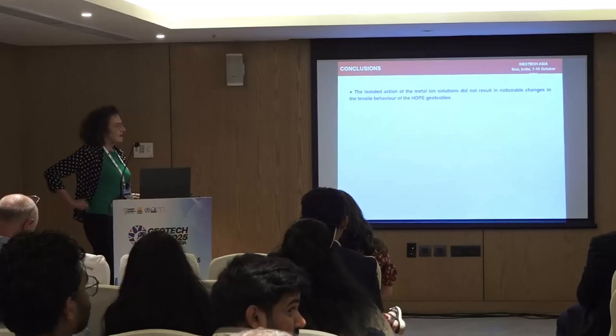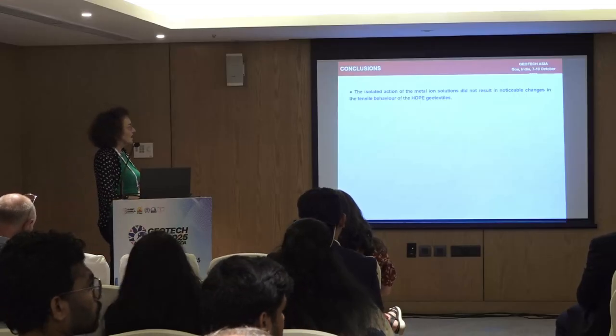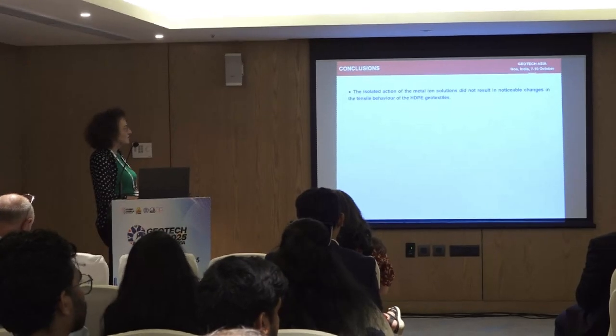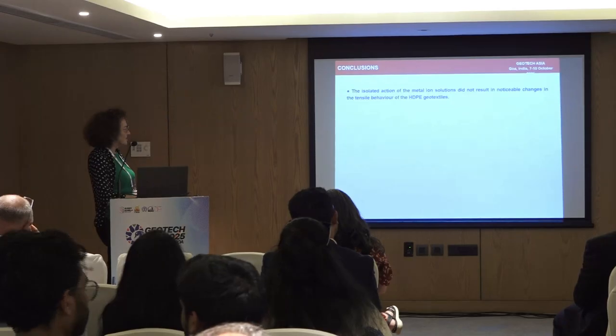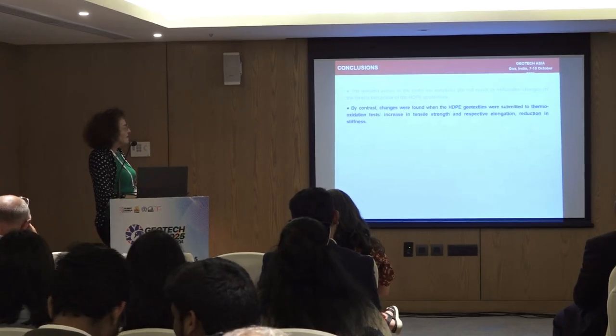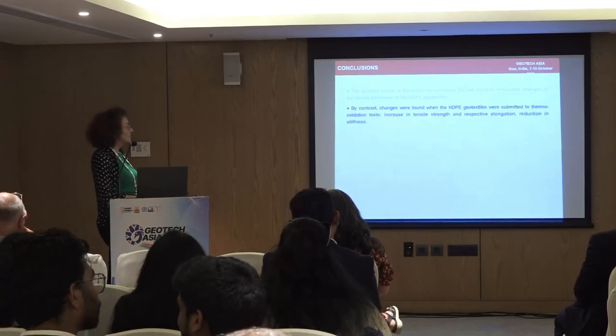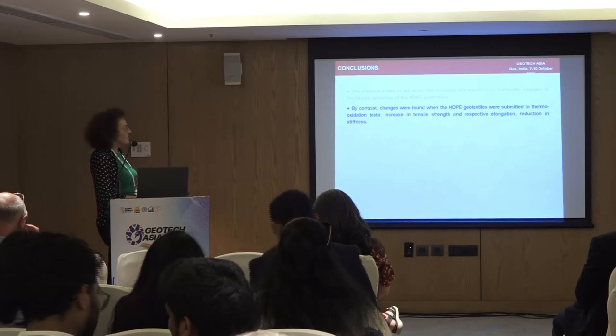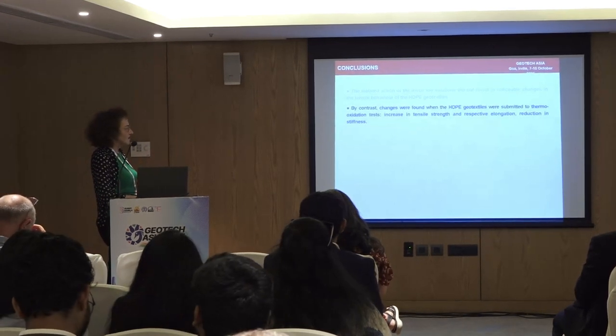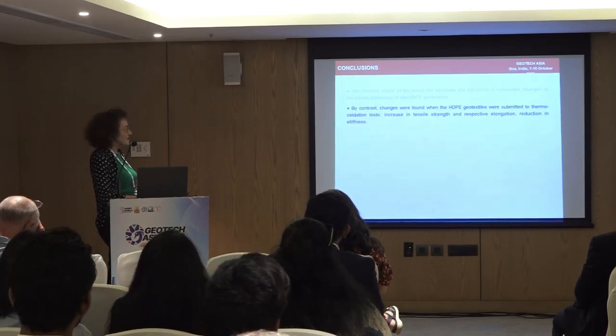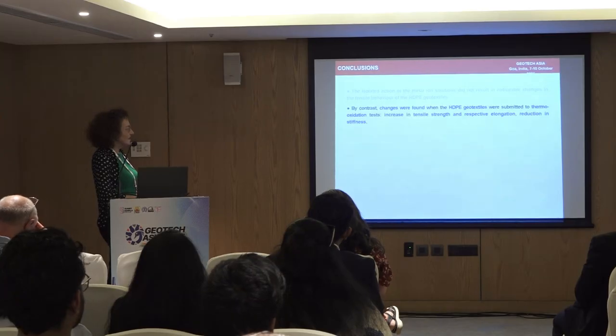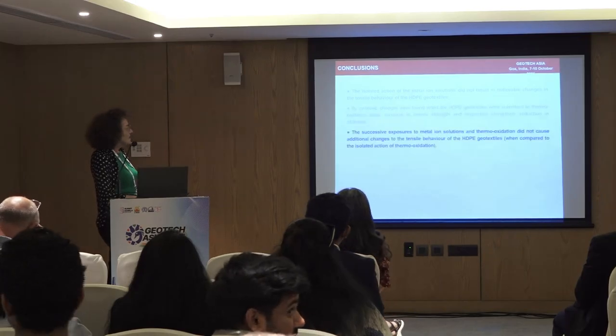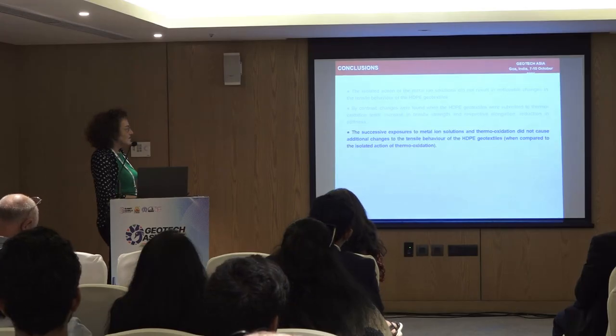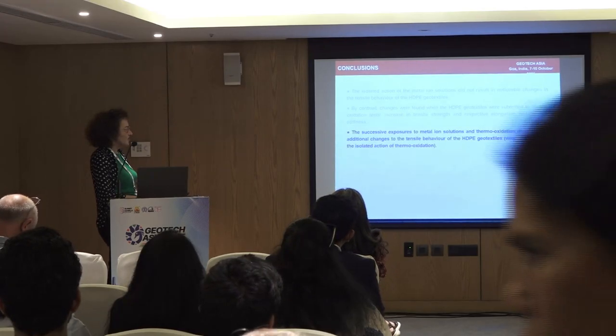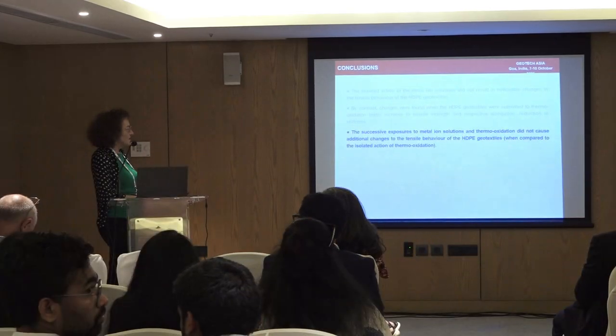Finally, we can say that the isolated action of the metal ion solution did not result in a noticeable change in the tensile behavior of HDPE geotextiles. On the other hand, we note change when those geotextiles were submitted to thermo-oxidation tests. This is increasing the tensile strength and elongation, and so reduction in stiffness. The successive exposure to metal ion solutions and thermo-oxidation did not cause additional change in the case of HDPE geotextiles.